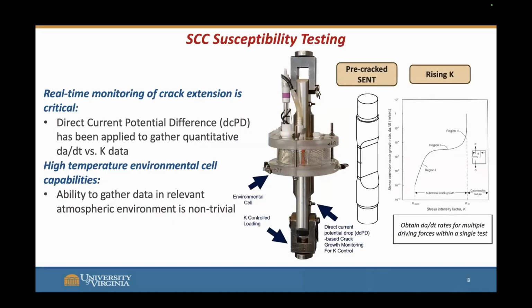And so my part of that task was to start developing a database for these crack growth kinetics with SCC. And specifically, we were looking at individual constituents and trying to find the boundaries of the worst and best case scenario, as we're the first attempt to do this within the US. And so we are just starting to try to figure out what actually matters, what's the worst case scenario, what's the best case.